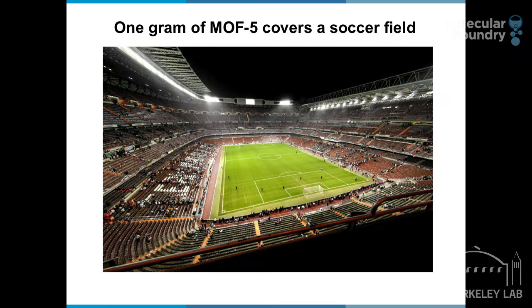We were very excited about this value because it essentially exceeded the record for all porous materials known up to that point. Just to give you an idea, what does 2,900 meters square per gram mean? If I take a gram of this material and I spread it on a flat surface, I would cover an entire soccer field. That's the kind of space, or real estate, let's call it, available to pack gas molecules like hydrogen, natural gas, and carbon dioxide, which I will be mentioning shortly.